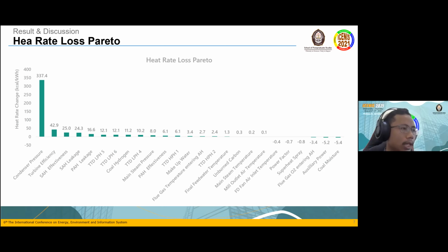And the last, the most significant boiler efficiency reduction factor is the increase in dry gas losses. These losses are caused by decreased air preheater effectiveness and increased air preheater leakage. A decrease in primary air heater effectiveness can be caused by pipe corrosion, pipe plugging, and pipe leaks. Meanwhile, a decrease in secondary air heater effectiveness can be caused by heating element corrosion, deformation, and blockage. An increase in primary air heater leakage was caused by leakage of the pipe heat exchanger. It can be due to fly ash erosion or corrosion. Meanwhile, an increase in secondary air preheater leakage can be caused by the radial air seal or axial seal gap of the air heater being too wide.